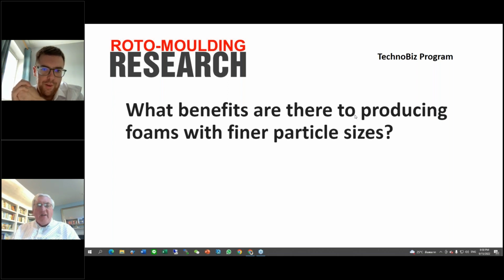Yeah, and certainly we found with a finer grind it would tend to clump in the mold, particularly around the areas where you were adding it through the hatch or whatever you're adding your second shot through, or around your drop box. You would tend to get clumping the finer the powder was. So the coarser the powder was, it flowed around the tool a lot more easily.